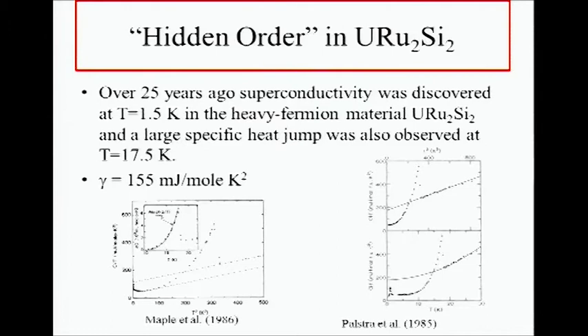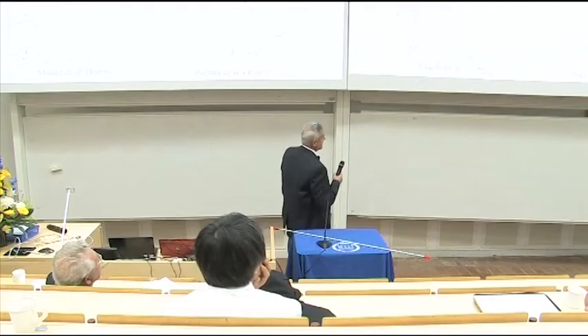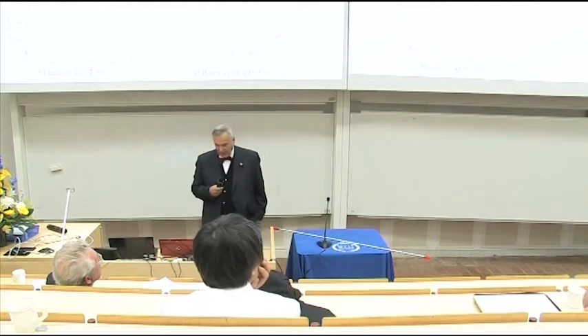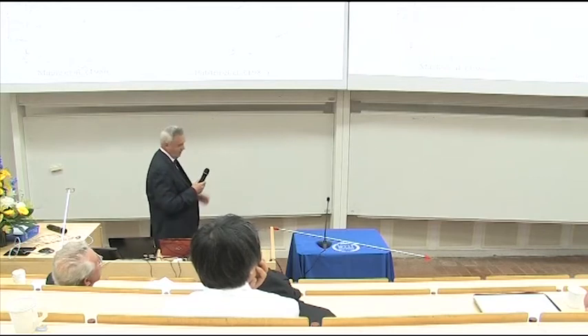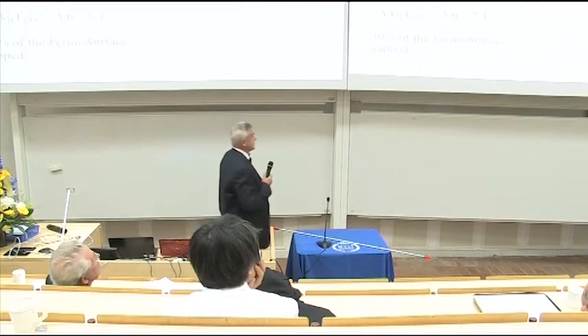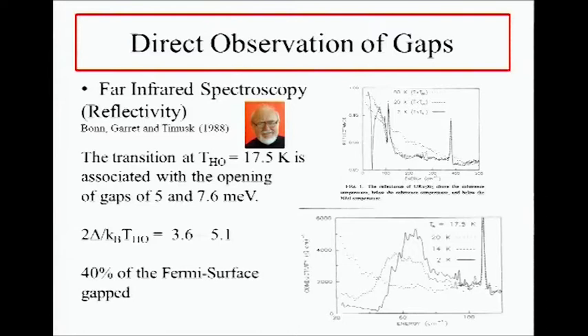This is a material which I think somebody mentioned has strong correlations, and when you get strong correlations, like in the one-dimensional Slater-Hubbard model, you get gaps. This is what this is all about - a material where as you cool it to 17 degrees you see this huge spike in the specific heat, this lambda-type transition, and at lower temperatures there's a superconducting transition. At 17K, a gap opens up in the transport properties, and you can actually see it in optical conductivity. So there's this huge gap.